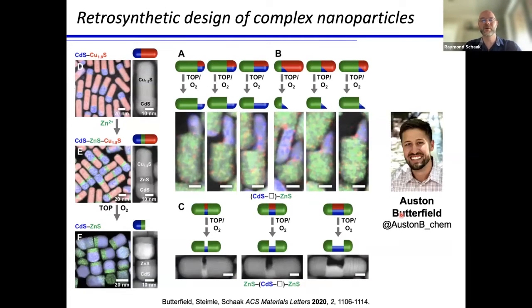And just very quickly to show where else this can go in the level of tunability, follow-up work by Auston last year in my group showed that basically using these design guidelines, the ability to make particles that have very precisely tuned regions, and then using that etching chemistry to remove any residual copper sulfide that was purposely put in there kind of as a placeholder that can be removed after the fact. We can make these particles with really tunable gaps. We can tune protrusions and lengths in different ways and make these really elaborate anisotropic particles with different semiconductors connected together.